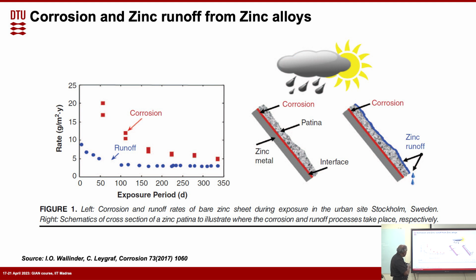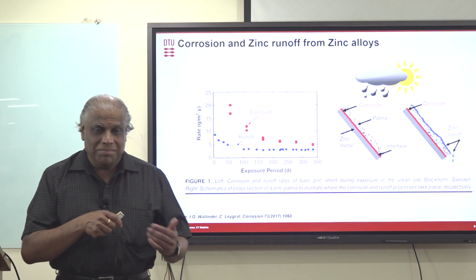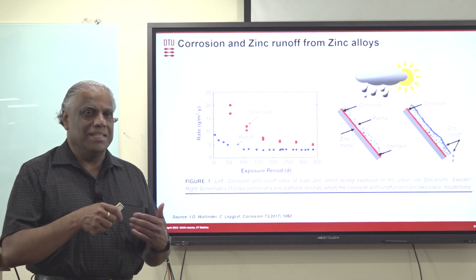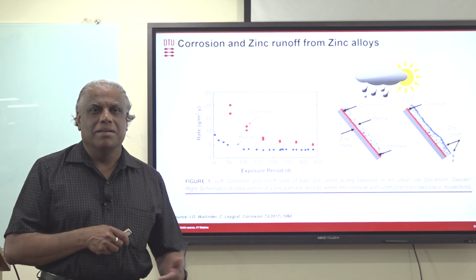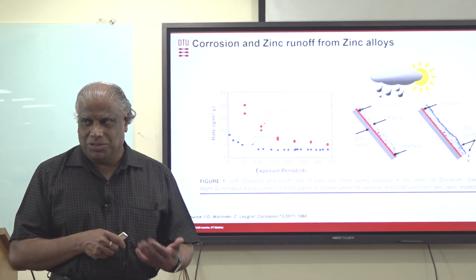And this shows the corrosion rate of the zinc. What you see here is that if you take these two together, the zinc corrosion rate is higher initially compared to the runoff rate, because the patina is quite small. But you can see that with time, the zinc corrosion rate and the patina dissolution rate are almost becoming the same, which means it is reaching a steady state condition. Whatever patina is forming, that patina is dissolved as well.